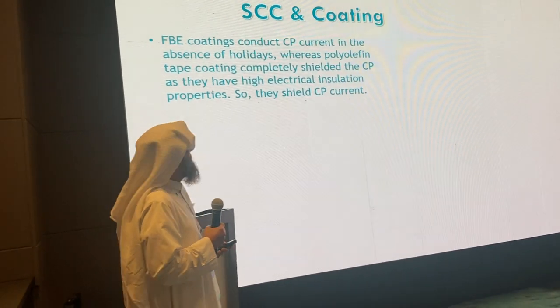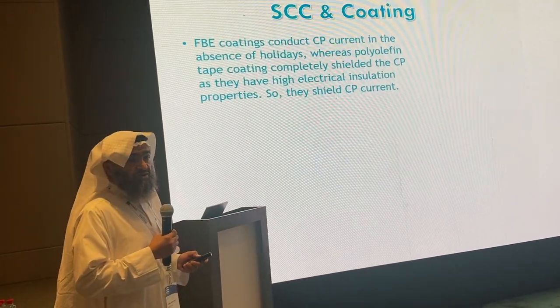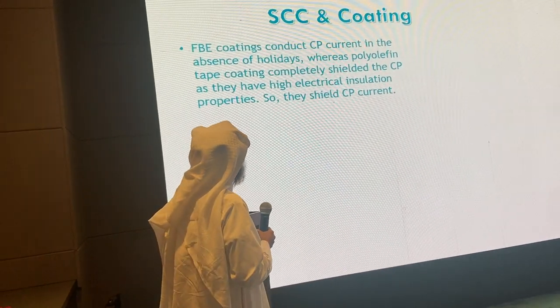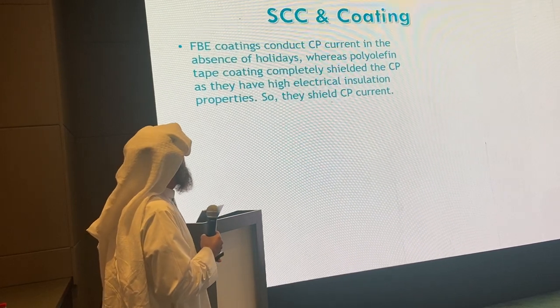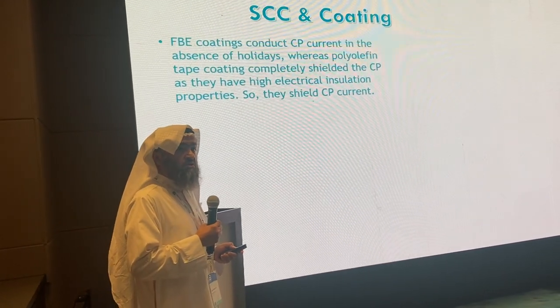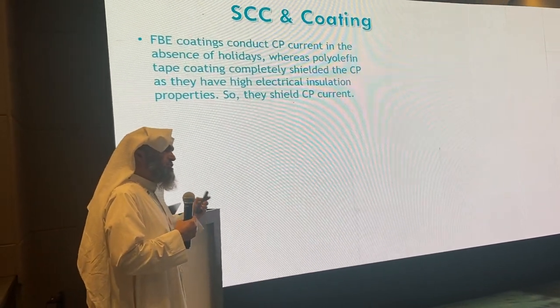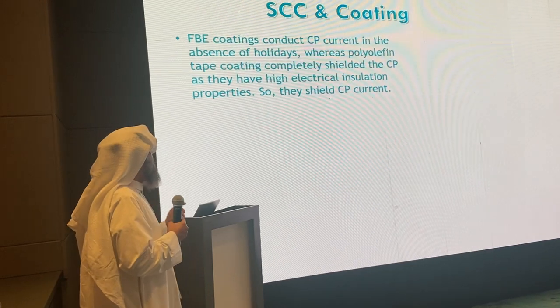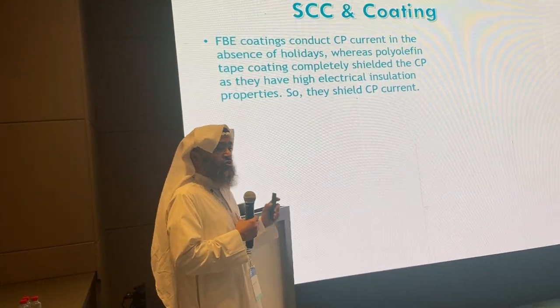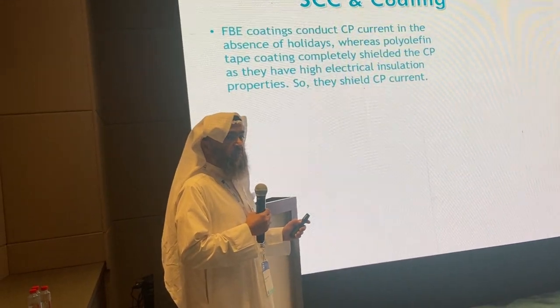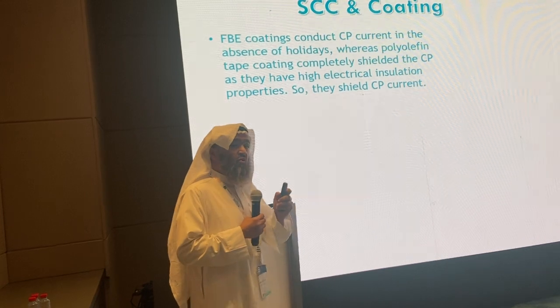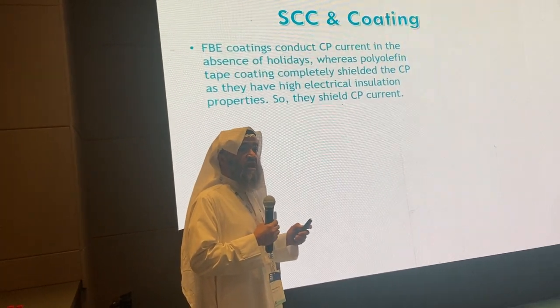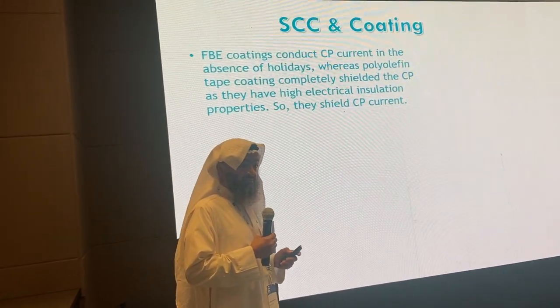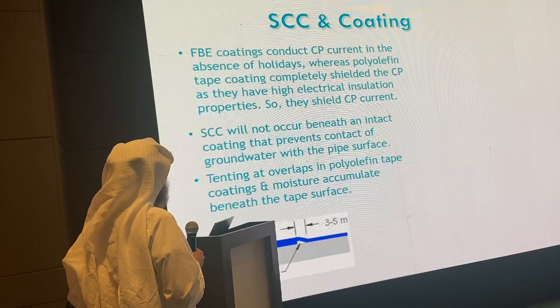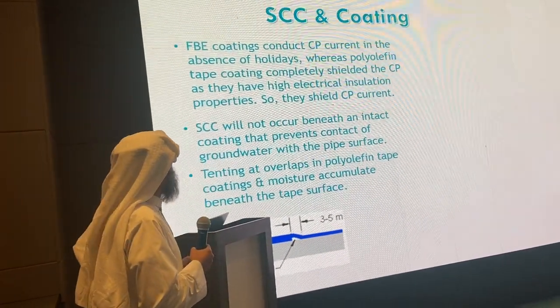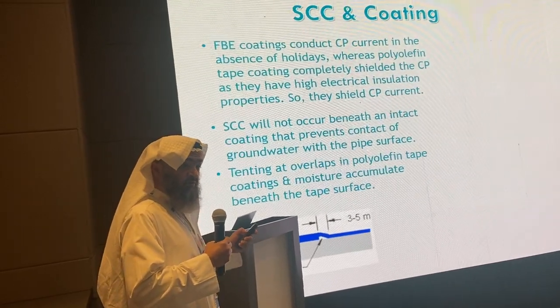FBE is known to conduct CP because its electrical resistivity is very low. So if there is no holiday, FBE will not cause corrosion, will not cause shielding of the cathodic protection. Whereas all polyolefin tapes do shield CP because their electrical resistivity is very high. Do you know, for example, that HSS heat shrink sleeves are tested at 25 kV? Stress corrosion cracking will not occur beneath an intact coating.